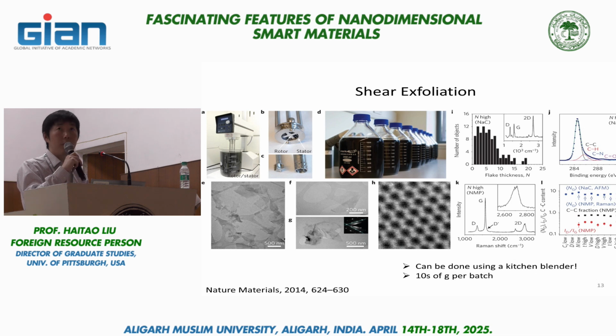If you look at the distribution here, in the top middle, to the right of the photos, that's the distribution of layer thickness. So you do see some significant fraction of single layer, but the average layer number is on the order of 5 to 10 layers per graphene flake. So still, on average, pretty thick flakes.